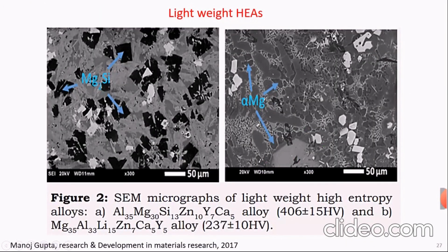We also have lightweight high entropy alloys, which are based on light elements like magnesium and aluminum. Actually, the main difference is that in the literature, some researchers observe that in lightweight high entropy alloys, we have more intermetallic amount compared to the heavyweight high entropy alloys. Here, as you can see, we have some magnesium silicide along with the alpha magnesium matrix. So don't worry when you find some intermetallics in your lightweight high entropy alloys. It's usual according to the literature. Here, for example, this is an aluminum, magnesium, silicon, zinc, yttrium, calcium high entropy alloy, and it showed good mechanical properties but has more intermetallics.